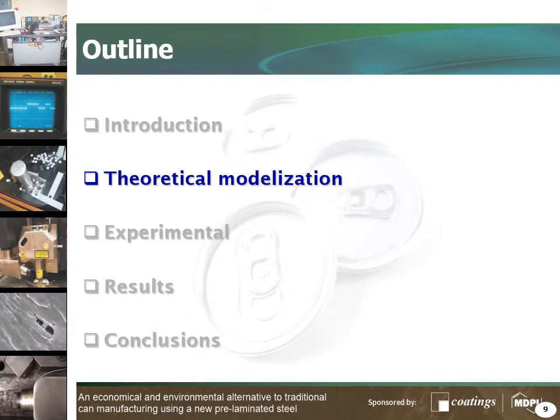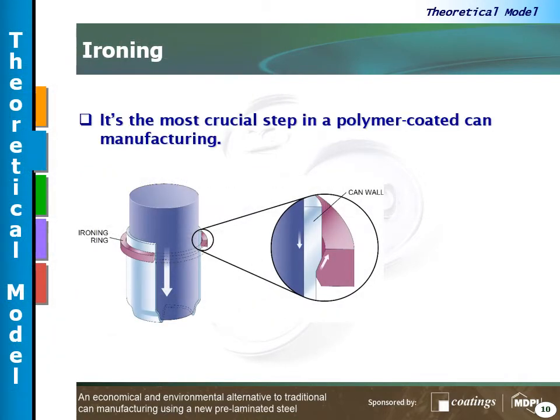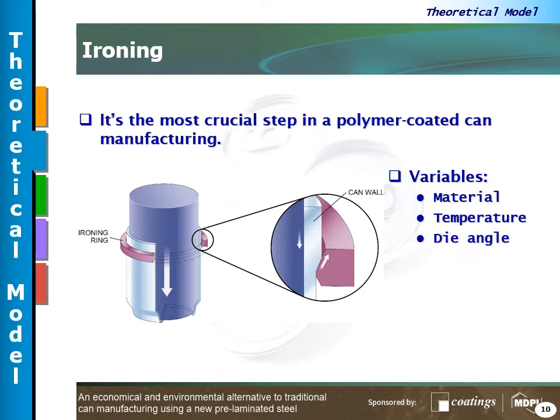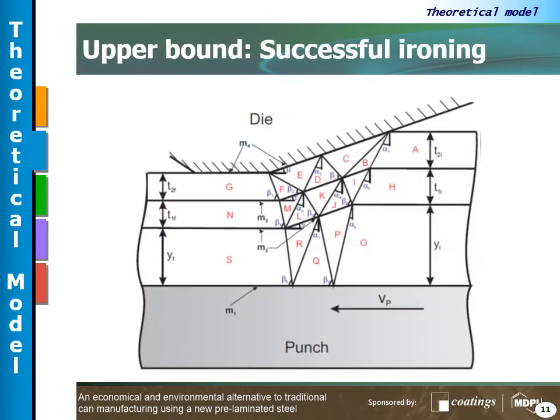I'm going to talk now about the theoretical modelization. Ironing is the most crucial step in a polymer coated can manufacturing, and the variables that we have considered are the material, temperature, die angle, reduction in thickness, and punch velocity. We have developed an upper bound model for successful ironing. Both polymer layers survive to the process.